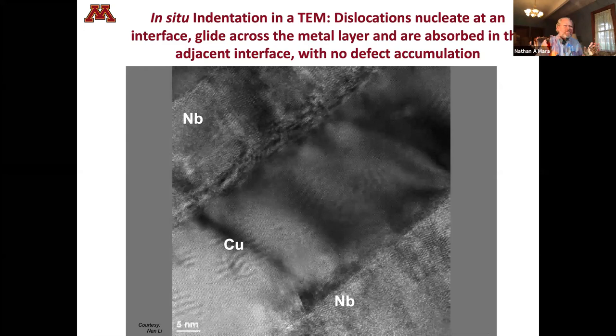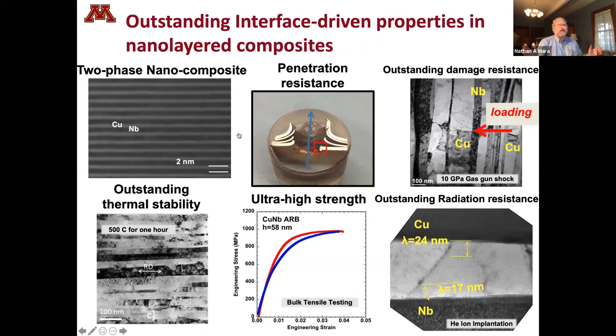So why do we care? Well, these interface-driven properties that arise from these interface structures are outstanding. So we can take two soft, nominally soft metals like copper, no different than what you would get at the hardware store. Niobium, another very, very soft metal. You start layering them up with just nanometers in their layer thickness, and you can increase things like penetration resistance for armor materials. They resist shock and shock-induced damage.